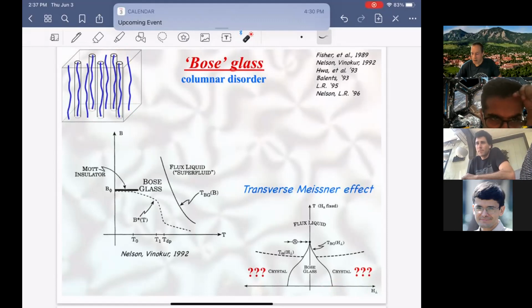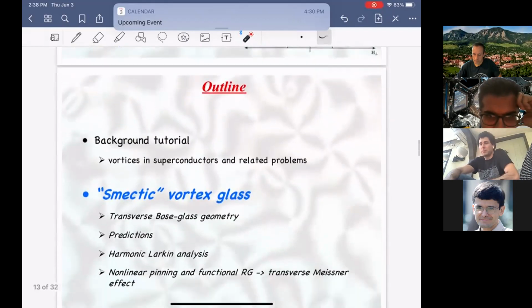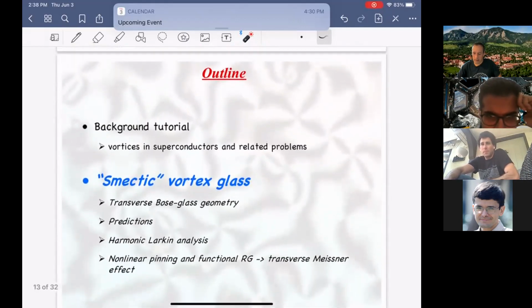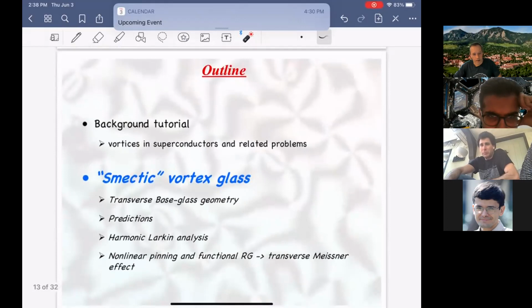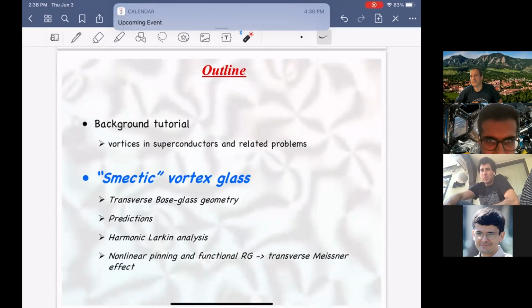And as a result, to really depin them and tear them away and to destroy this phase at low temperatures, you need to apply a critical value of the field. So this is like the HC1 for the transverse field, or the tilting angle. So, okay, with this background, I'm going to stop, and we can take a break before I launch into the Smectic Vortex Glass and the related stuff.